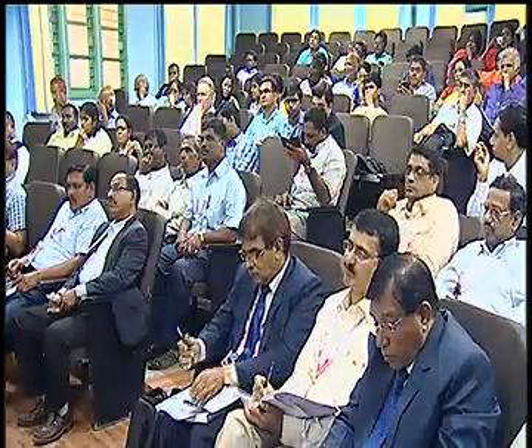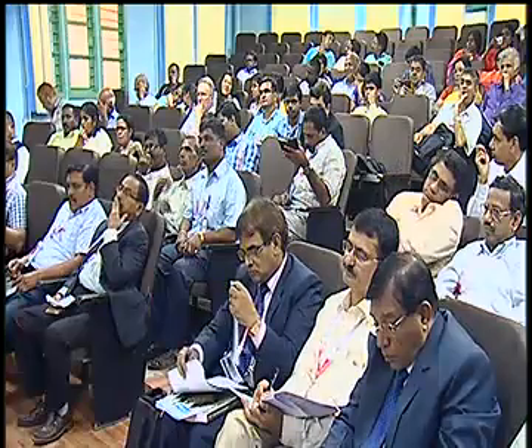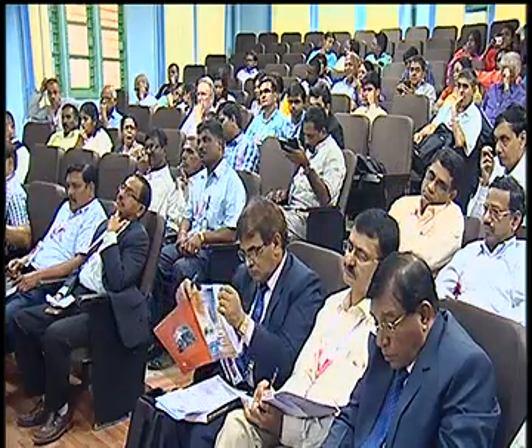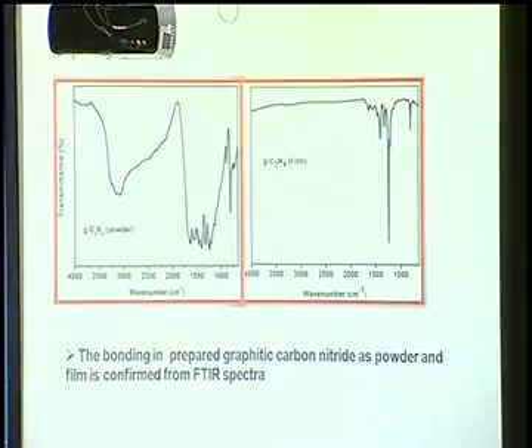This is a UV-visible DRS study of the powder as well as the thin film. Both materials could absorb visible light irradiation. And this is the FTIR spectra. In the FTIR spectra, all kinds of bonding, like the bonding due to the tri-s-triazine units, the carbon-nitrogen single bond and the carbon-nitrogen double bond, are confirmed. But in the case of the powder, I found a broad absorption at around 3000 to 3500, which is mostly due to surface-adsorbed water molecules. In the thin film, although this peak is there, it is very weak.